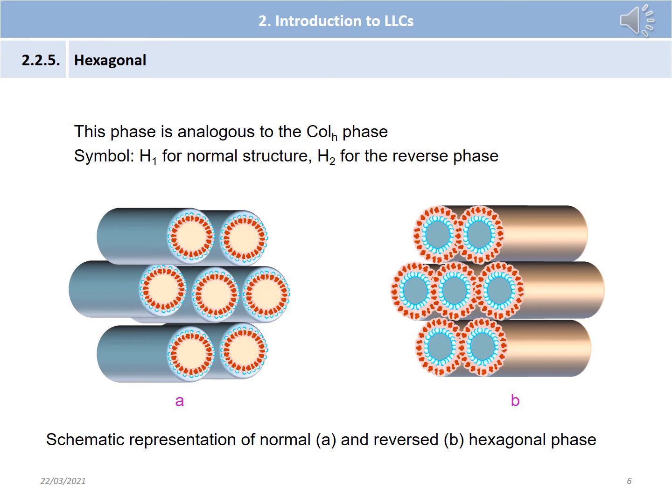In anhydrous organic solvents, with low water content, the structure is reversed and the hydrophilic polar groups now form the inner core and are shielded from the non-aqueous environment by a layer of hydrocarbon chains. These are called reverse hexagonal phase or reverse middle phase. Also, when large quantities of non-ionic surfactant are added to the system, a hexagonal structure and the solution containing reversed micelles may be formed. The hexagonal phase is much stiffer than the lamellar phase. The hexagonal mesophases composed of oleyl glycerate and phytanyl glycerate have shown great potential in drug delivery.